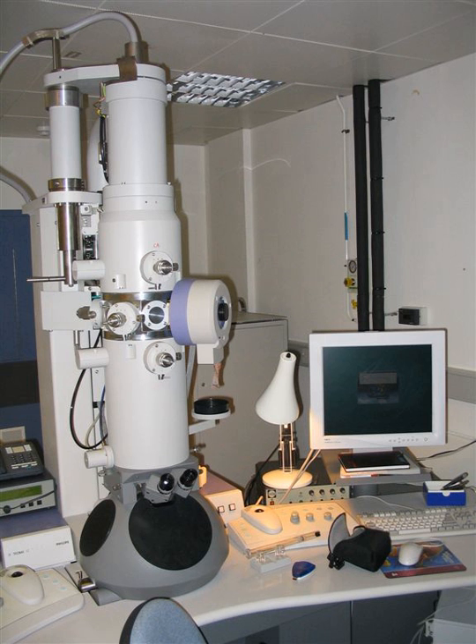The cold fractured surface, sometimes etched by increasing the temperature to about minus 100 degrees Celsius for several minutes to let some ice sublime, is then shadowed with evaporated platinum or gold at an average angle of 45 degrees in a high vacuum evaporator. The second coat of carbon, evaporated perpendicular to the average surface plane, is often performed to improve the stability of the replica coating.